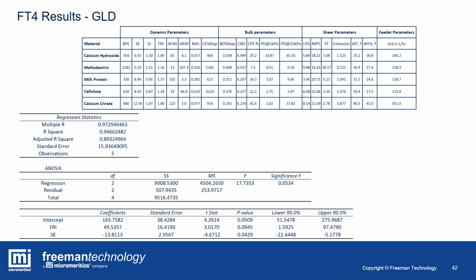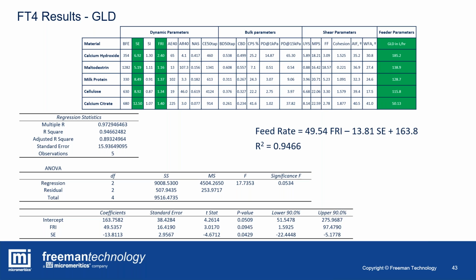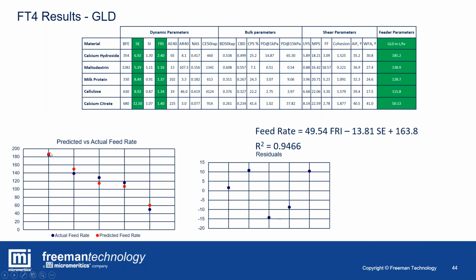And so we did the MLR regression analysis. That found a pretty robust R squared of 0.95 relationship between feed rate and the strain rate, or the flowability, the flow rate index properties, and the unconfined flow behavior, the specific energy. Really, they were considered the only two that were needed in order to predict with pretty decent accuracy the expected volumetric feed rate. If we look at that as a function of predicted versus calculated, you can see for the 5 materials the match is pretty good.